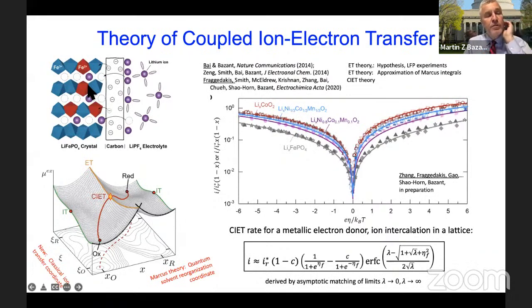And what we argued is that the rate limiting step is actually when the ion goes in, an electron has to reduce a nearby site in the crystal. In this case, the iron goes from +3 to +2. And in fact, lithium iron phosphate doesn't even work as a battery material unless it has a carbon coating. So basically you need to supply the electrons to the material and then they sort of hop in. And we argue that it would be according to this coupled ion electron transfer process. And the full theory of electron transfer I published with my student Dimitrios Fragadakis in 2020.